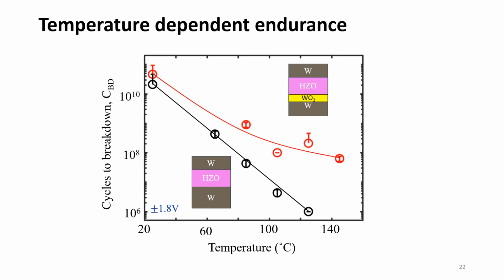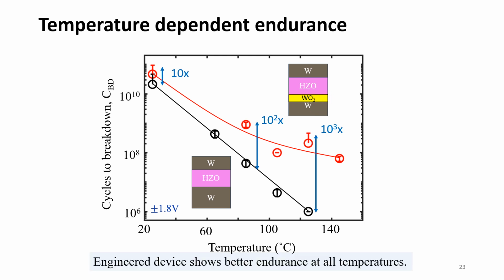However, in the case of the tungsten oxide device, or the ORL device, we can clearly see that we're having higher endurance at each temperature due to the presence of this tungsten oxide layer, and this endurance enhancement is up to 3 orders of magnitude at 125 degrees Celsius. So due to having tungsten oxide, we are having higher endurance at all temperatures.